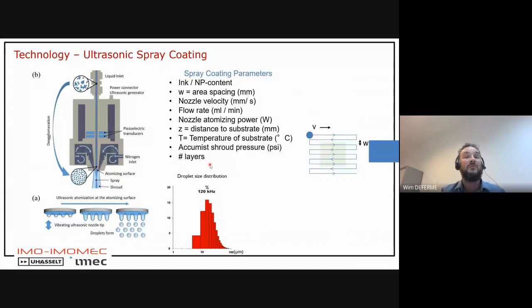And finally, you can also think about coating and overcoating, so you can put several layers on top of each other, because I was discussing the thinnest size we can go for, or the thickness, going around, let's say, 30 nanometers. But of course, if you want to go to layers having several micrometers thickness, you can, on the one hand, increase the concentration. The ultrasonic spray coater can go from very low viscous inks, water-based inks or viscosity comparable to water, towards quite high viscous inks. But also putting more layers on top will increase the thickness.